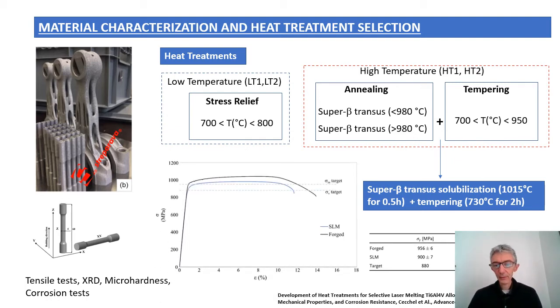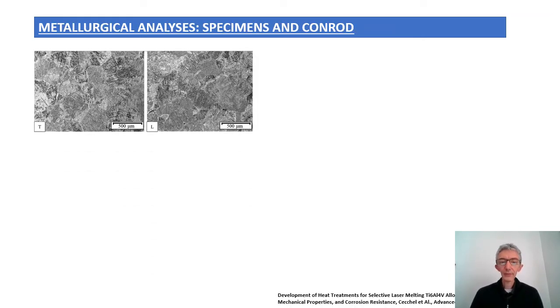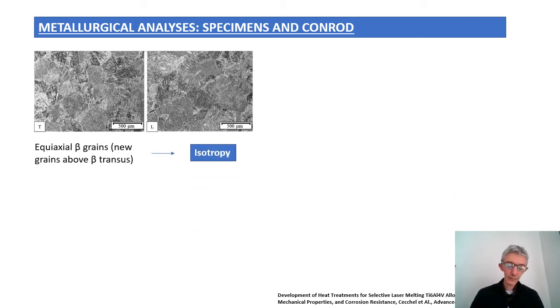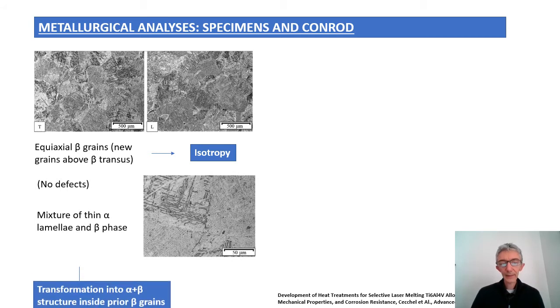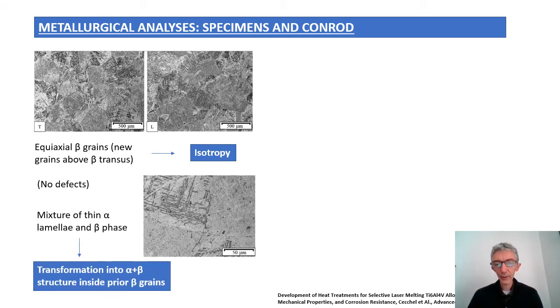And here we can see a comparison of the stress strain curve of the heat treated SLM material in comparison with the forged equivalent alloy. In parallel, they also carried out metallurgical analysis on the microstructure, and the main findings were that the effect of the heat treatment was to induce isotropy of the microstructure, and in general, the transformation into alpha plus beta structure inside prior beta grains.